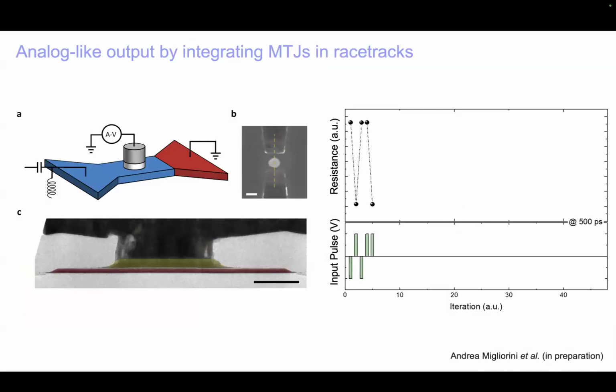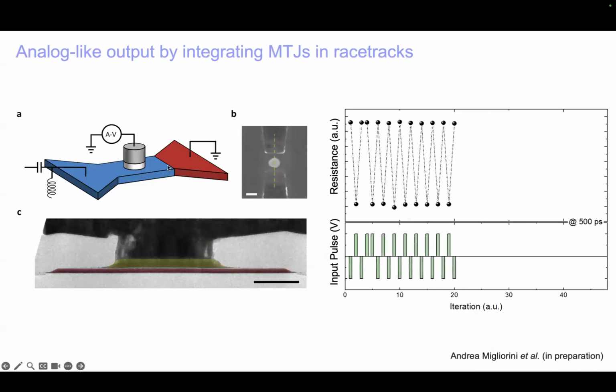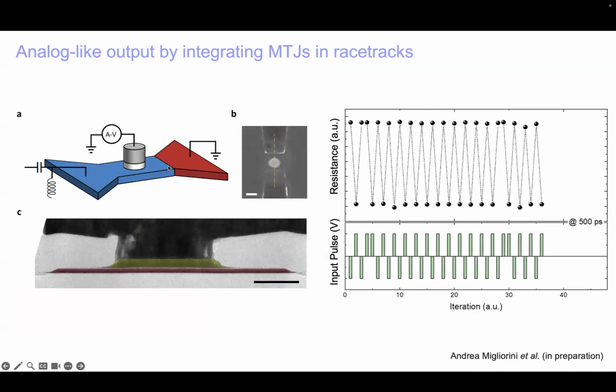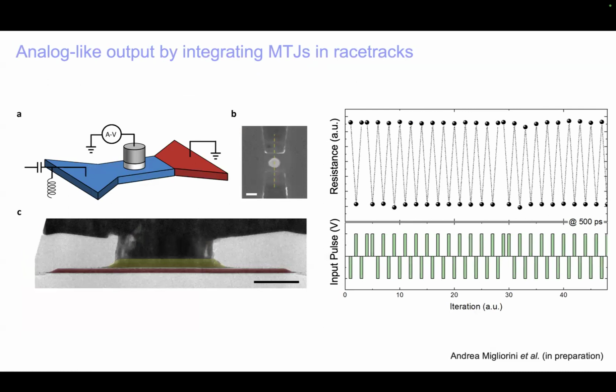And now I just wanted to mention, we're also very interested in a simpler racetrack shown here on the left-hand side, where we integrate a single magnetic tunneling junction on top of a racetrack, and we move the domain wall from the right-hand side to the left-hand side by a single current pulse. Here we're using current pulses that are only 500 picoseconds long, and we're detecting the change in state of the tunnel junction. So you can see we can build a racetrack which is super fast with a single domain wall. This type of racetrack could replace the fastest memory today, which is static random access memory, would have a smaller form factor, and would be non-volatile. This is a very exciting possibility.